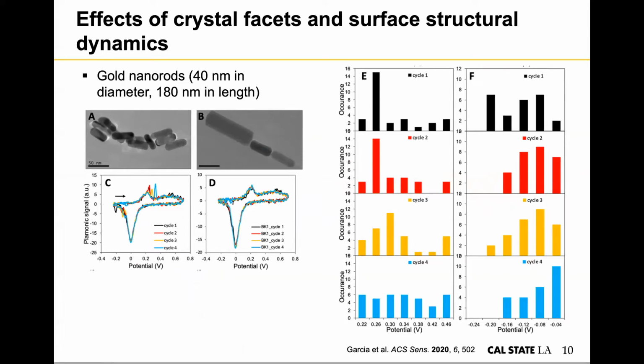With gold nanorods, we did some TEM and noticed that with the same batch of nanorods, some rods are more round and some have very clear facets. And when we obtain the CVs from individual nanorods, we actually observe that different nanorods have different minor peaks for the oxidation part and for the reduction part. So here we show one example.